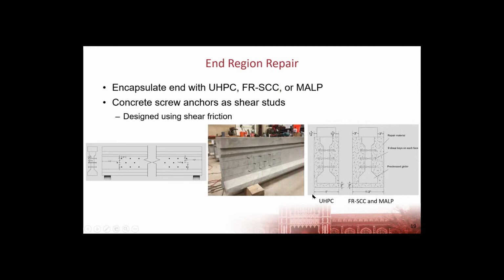For the UHPC, we used a minimum thickness of 1.5 inches on the bottom flange. We had 2 inches below the beam, and then we used a constant cross section all the way up. So we had a 4.5 inch thickness on the web, and then a 3 inch thickness on the top flange of the beam, and we went to the bottom of our simulated deck.